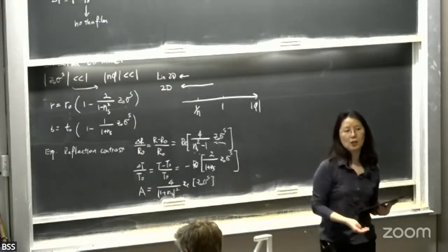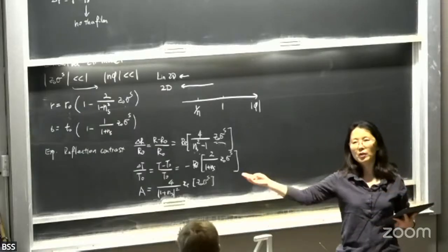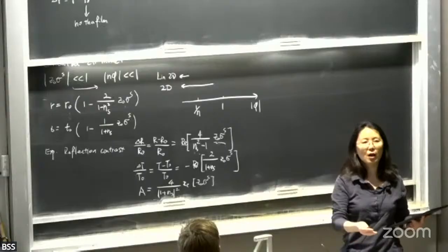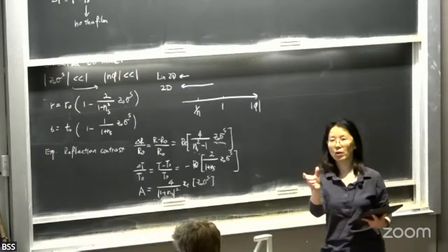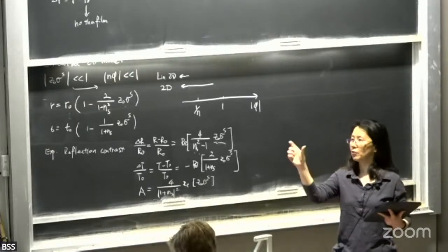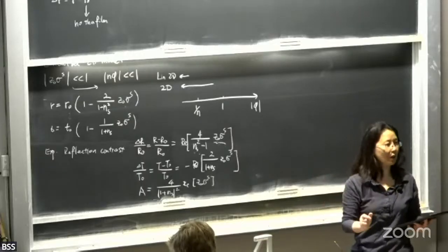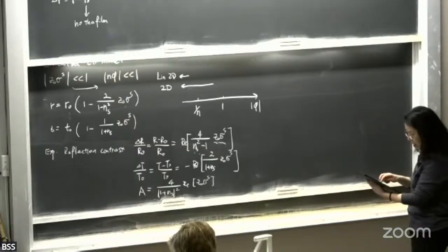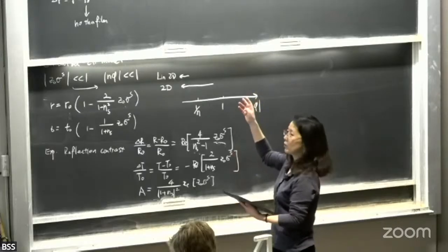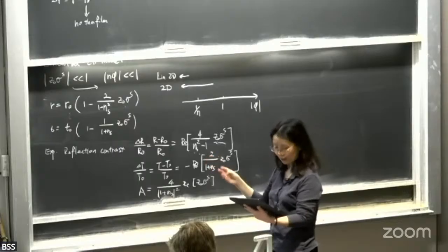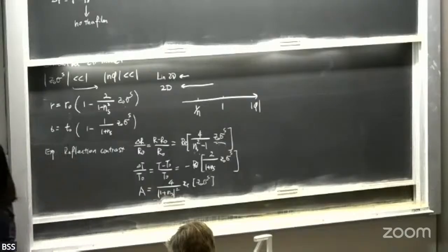But the complication here is that, remember, the Kramers-Kronig relation is for infinite spectrum. So you need to have low to very high spectrum. And for optical measurements with very limited range of frequencies or energy, the Kramers-Kronig is not very good. Okay, so those are the complications. Okay, so now let's take a look at some real material and see whether any of those approximations are good. Okay, so I'm just going to show you some simulation from this paper.